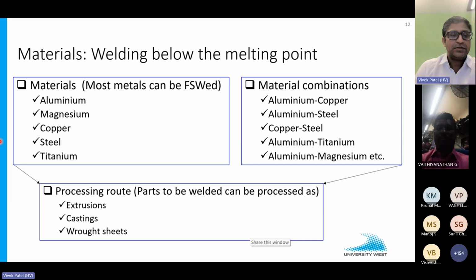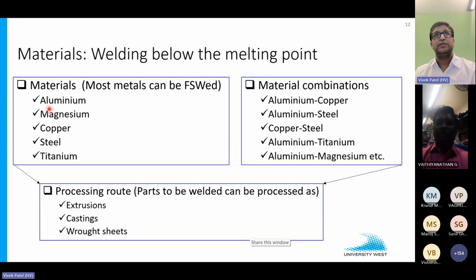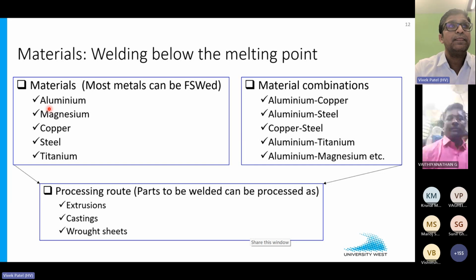So the materials. Most metals can be welded by friction stir welding, and we start with aluminum. There is significant evidence for aluminum. All the aluminum alloys, from pure aluminum to the highest strength aluminum, you can weld by friction stir welding. And luckily, we have the ISO standard for aluminum friction stir welding. So there is no doubt about putting it into production and running the components, whether in the lab or on the road, in shipbuilding or aerospace.